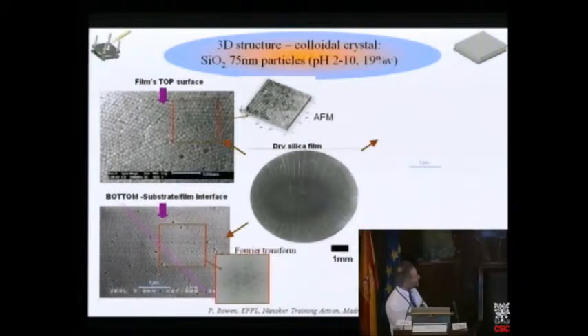So basically, you end up with this catastrophic cracking. And the catastrophic cracking comes exactly at the start of the first falling period of drying. So it's exactly where you expect the classical problem: you get inhomogeneous capillary forces because you have inhomogeneous evaporation from within the structure, because pore sizes and the pore structure are not identical.